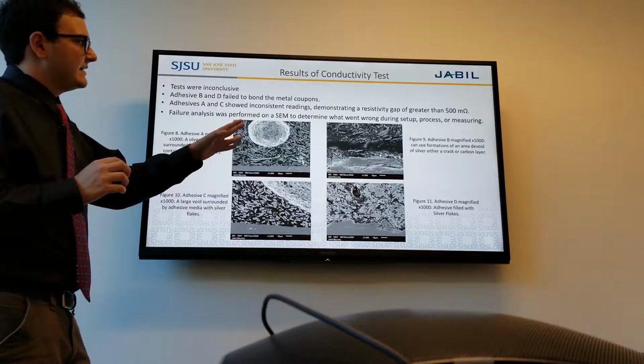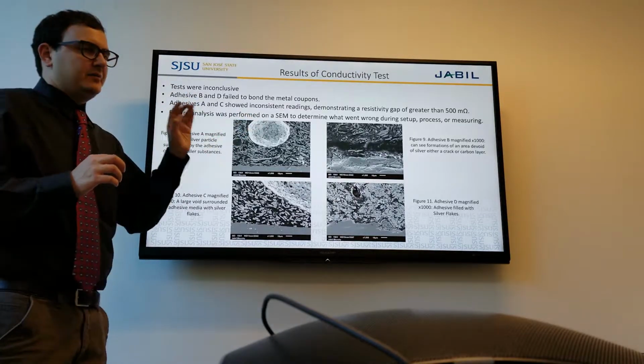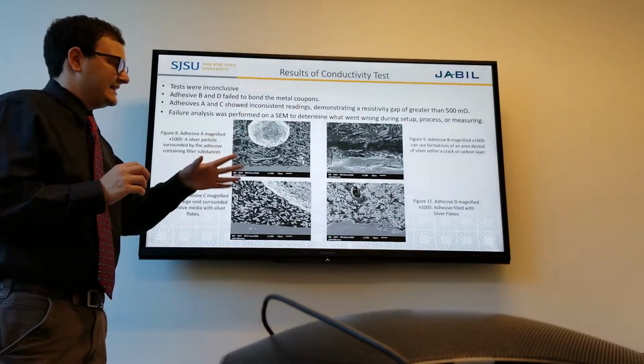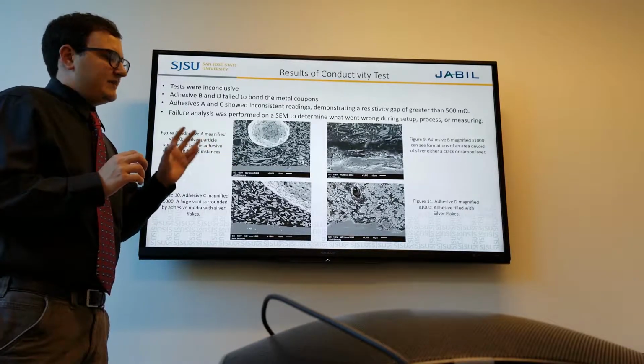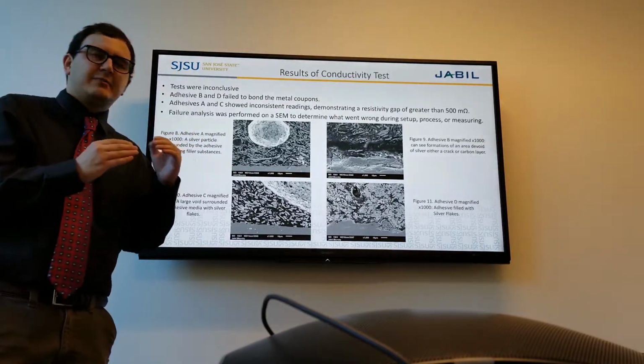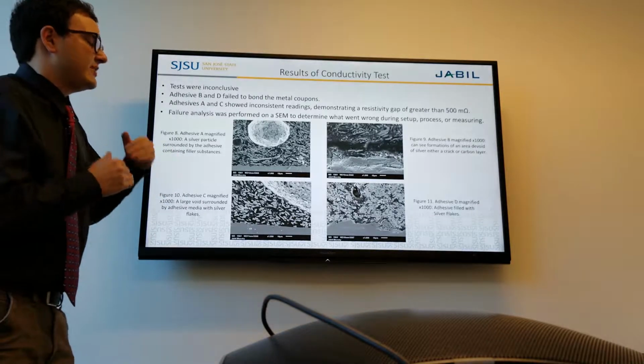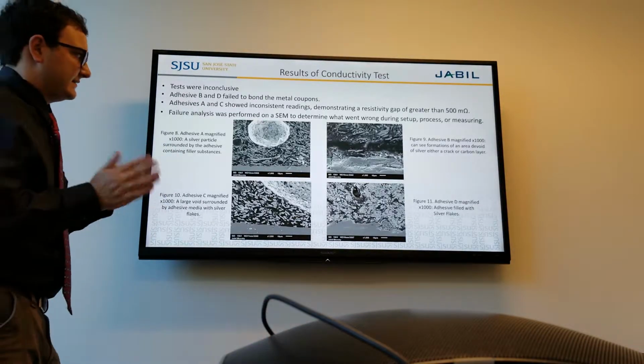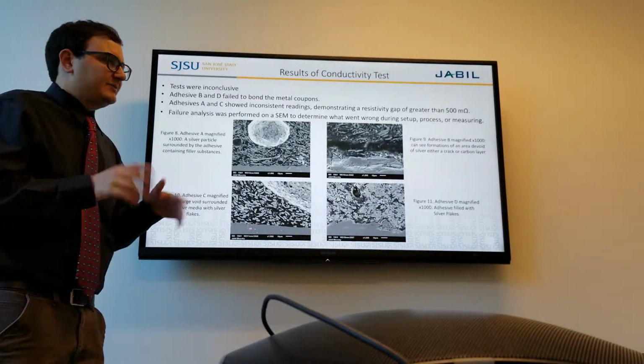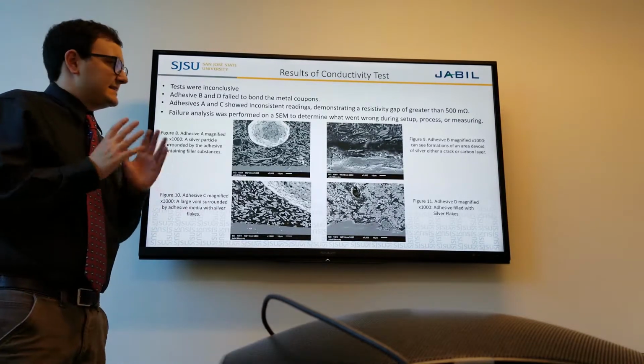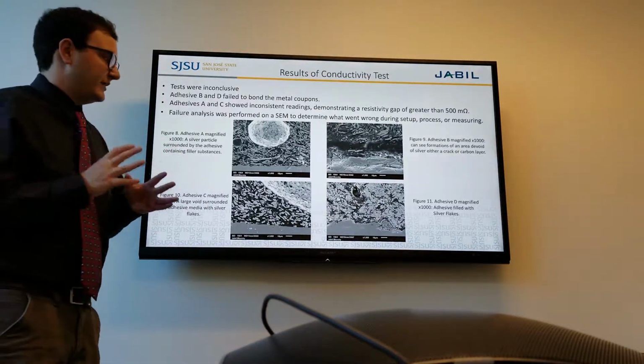For adhesive B, you can see a formation of a layer, or it could be a crack with contamination in it. The problem with that was that it formed weak points within that adhesive bond, points where the adhesive snapped, basically, on the microscopic level.